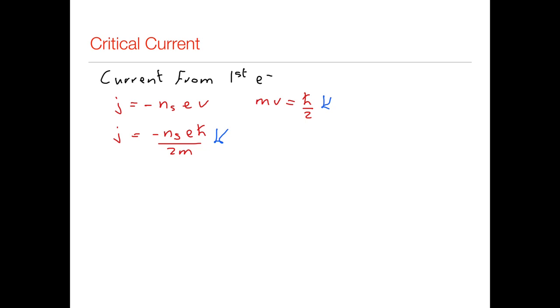And using the formula from previous, subbing that in, that will give me that delta E is equal to h bar kf J over e ns. Okay, so just perhaps pause the video for a second, look back at the previous slide and convince yourself that this is the case. So this tells me that the energy difference is related to the amount of current that flows. Okay, so the higher the current, the higher the energy difference between the superconducting state and the normal state.